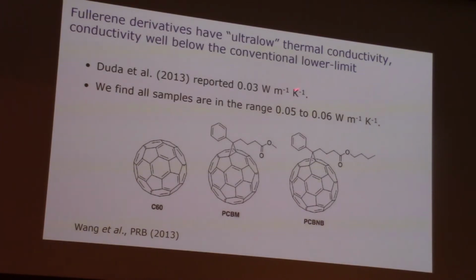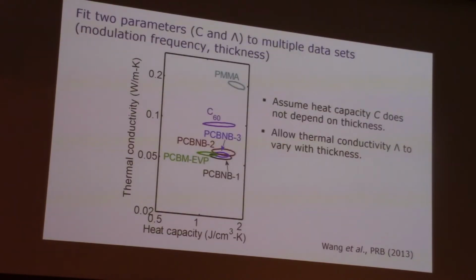And there was a report of very, very low thermal conductivities in these classes of materials, which we were not able to reproduce. I suspect there were little problems with the characterization of thicknesses and things like that. But we certainly found very low thermal conductivities, also very comparable to the tungsten diselenide, in these functionalized fullerene derivatives, right? And this is one summary of some of that data.